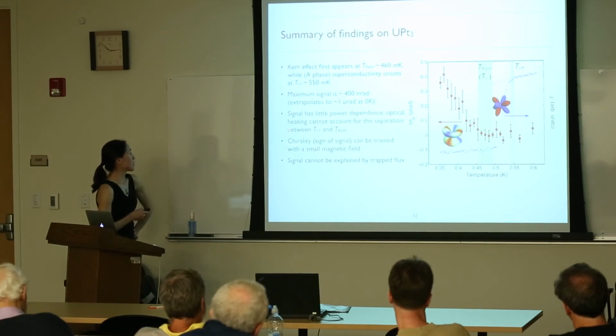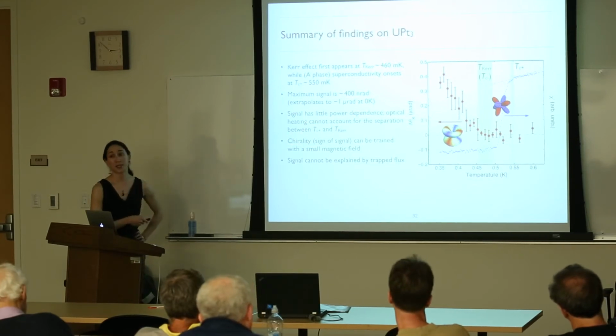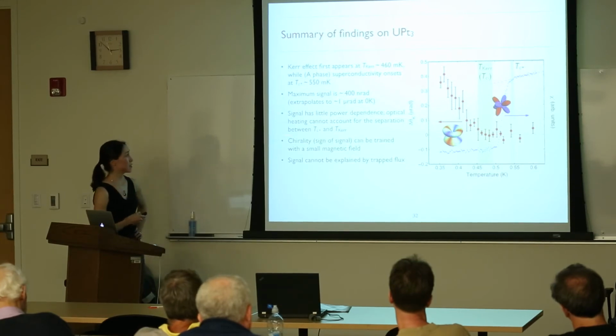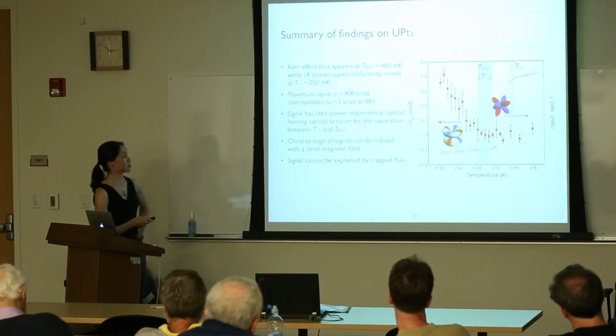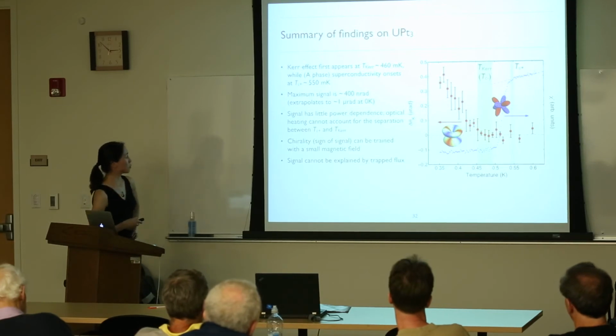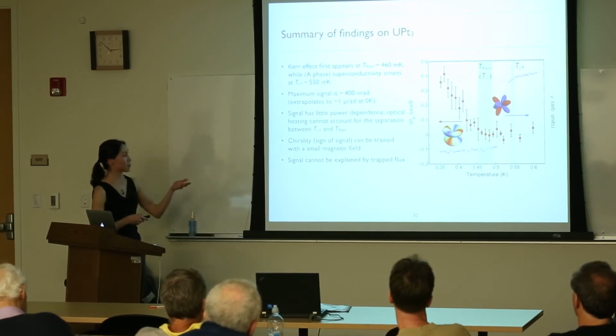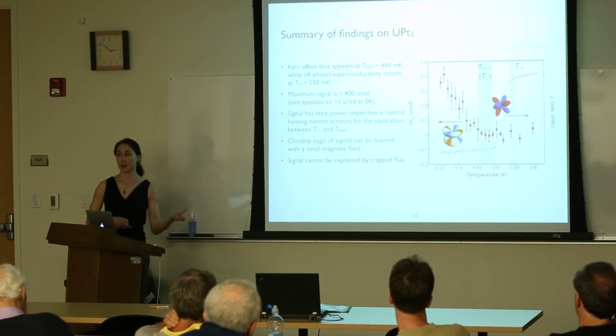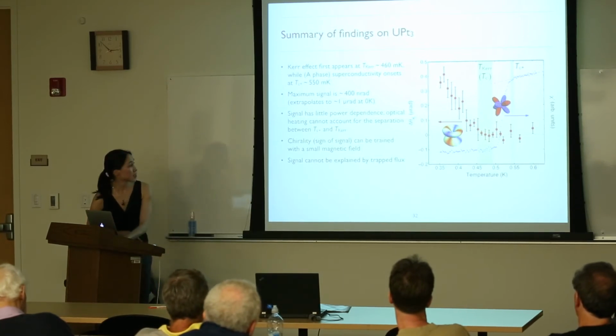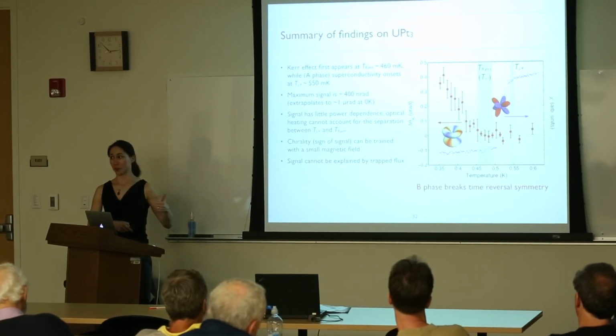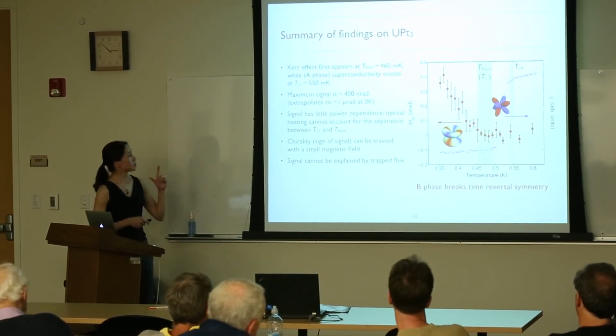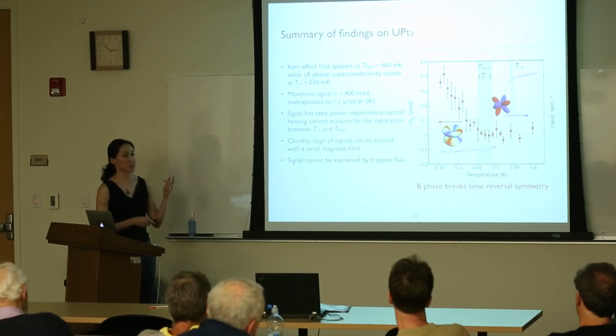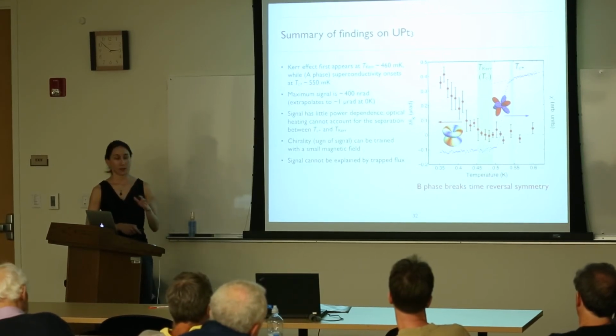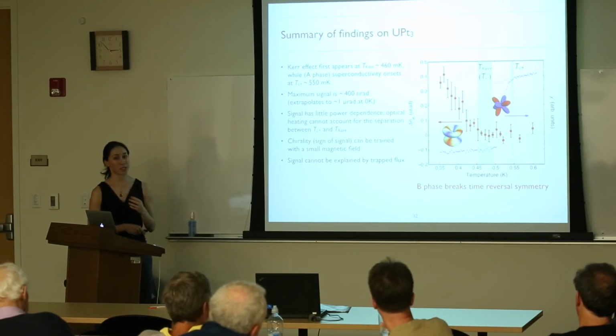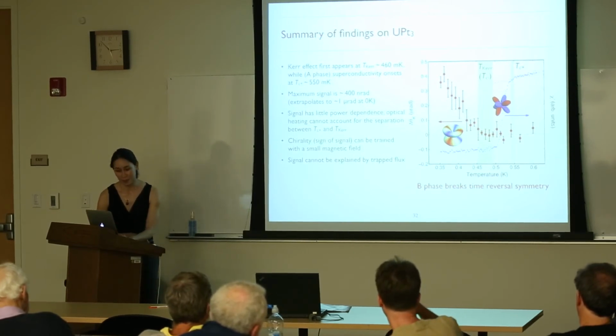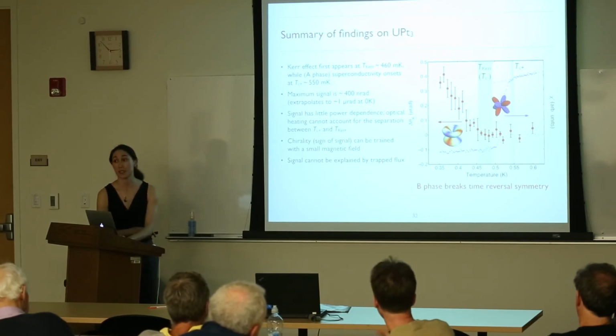I've taken sample heating and power dependence into account. So we can't account for the separation between these two transitions by optical heating. Moreover, the chirality or the sign of the signal can be trained with a magnetic field, and it doesn't appear to be coming from trapped flux. So all of these things together suggest that time reversal symmetry is broken, for one, and for two, that the time reversal symmetry breaking happens in the B phase and not in the A phase. This is consistent with our E2U picture and several others, but really the main conclusion is that of broken time reversal symmetry.